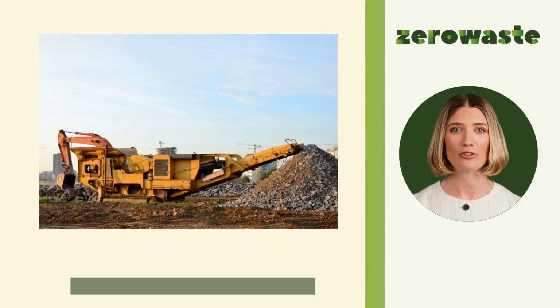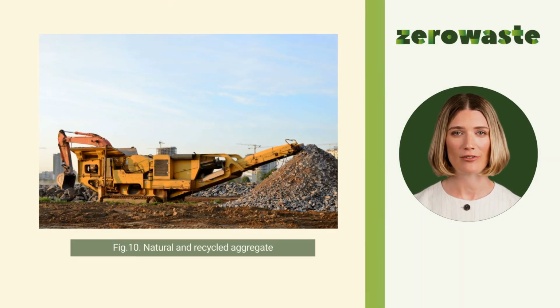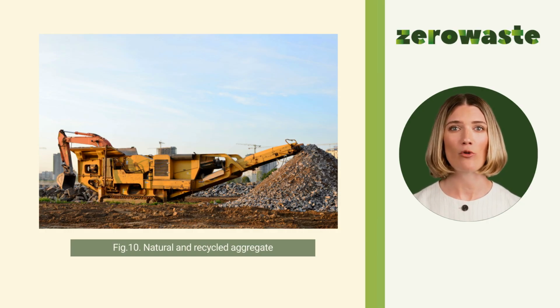The compressive, flexural, and tensile strengths of recycled concrete are also affected. Tests show that when 100% of natural aggregate is replaced, compressive strength can be 15 to 40% lower. At all testing ages, 1, 4, 7, 28, and 90 days, the compressive strength of recycled concrete is lower than that of natural aggregate concrete. Flexural strength with full replacement of coarse aggregate is either the same or up to 10% lower. Tensile strength decreases by 12 to 31%. Replacing fine aggregate reduces flexural strength by about 20%. However, replacing only 20% of natural aggregate has negligible effects. The modulus of elasticity decreases by 6 to 33% with full replacement.